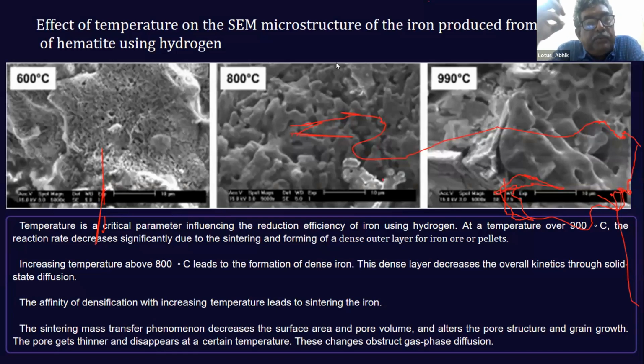What happens if the porosity of the iron ore reduces? That the gas, like the carbon gas or the hydrogen gas, cannot go inside it, and so cannot diffuse inside it. And if it can't diffuse inside it, it cannot react with the iron inside. So if you can't react with the iron inside, then you are not extracting the iron. So the process will be slower and slower. Okay, so this is what is happening with the temperature. This is another very challenging part if pure hydrogen is being used.